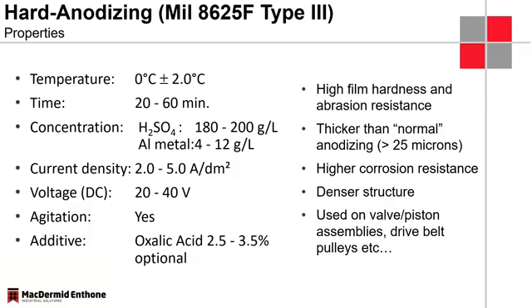What we also achieve here is we have a much denser pore structure, and there's a lot more strength within these pores because we don't actually dissolve aluminum out of these pores and reduce the wall thickness of these pores. Therefore, these coatings are much harder and have much better wear resistance for applications like valves, any sort of moving parts.